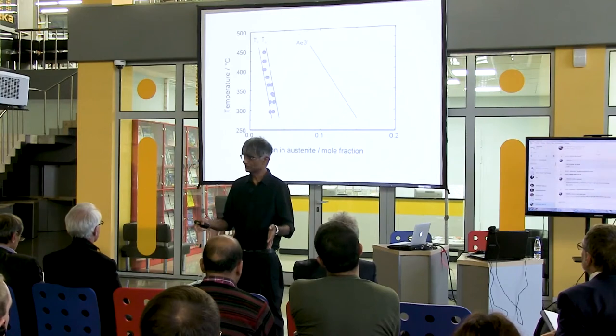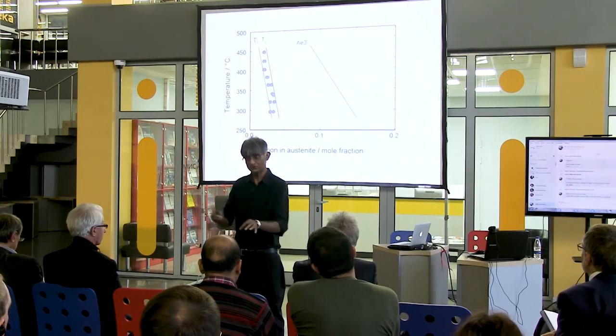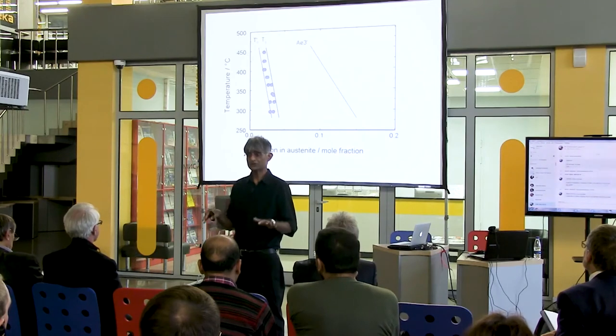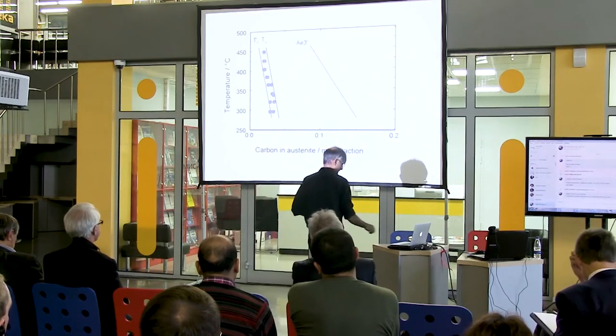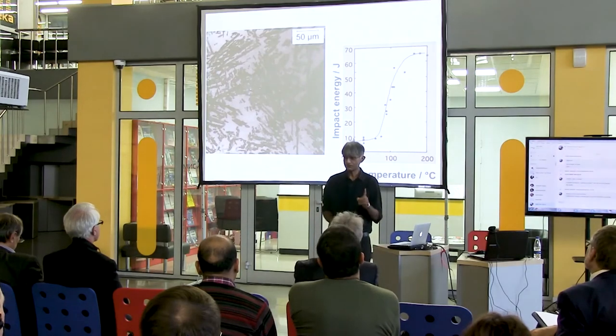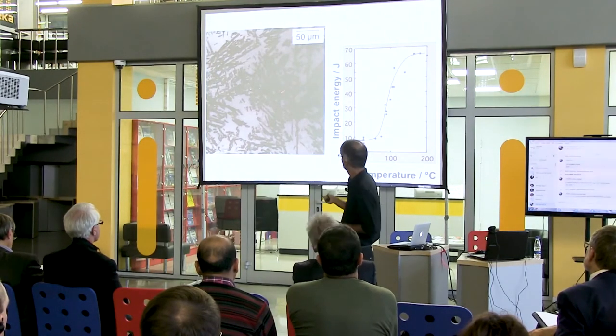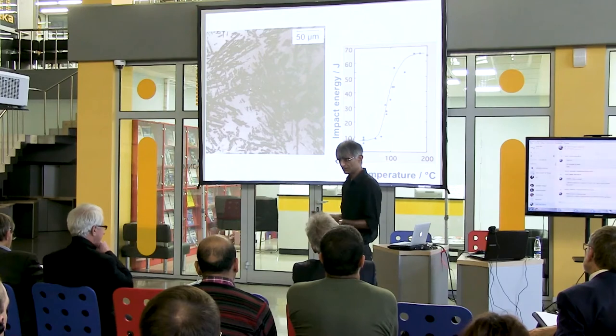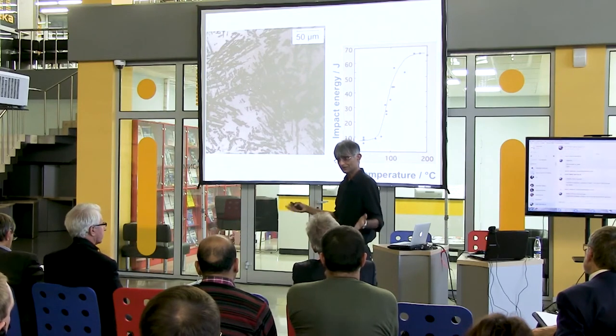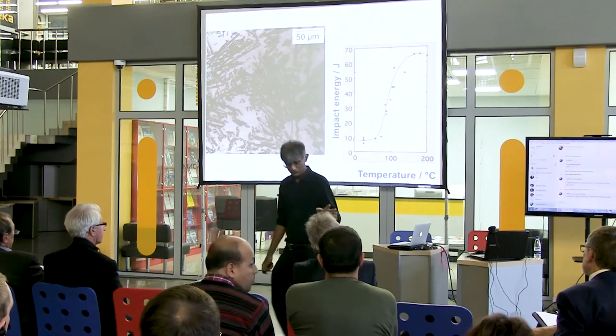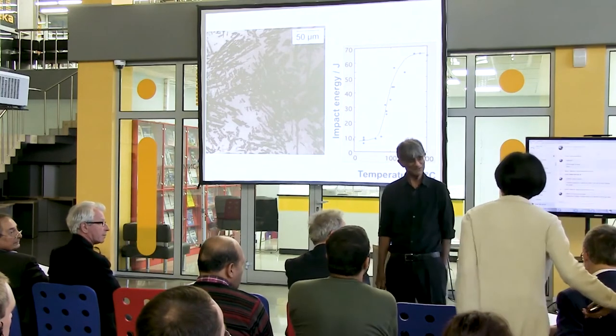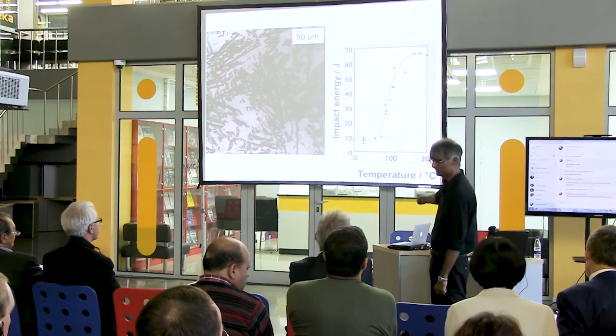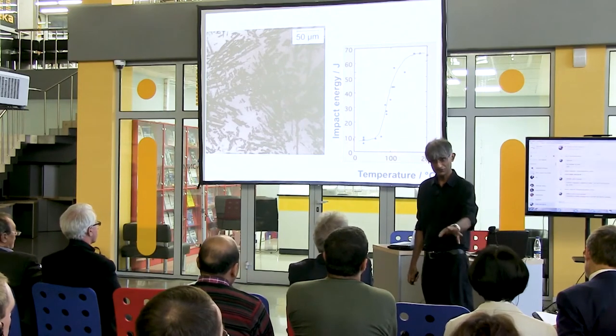This is a macroscopic measurement — it doesn't take account of the inhomogeneous distribution of carbon. On average, the reaction will stop when the carbon concentration anywhere in the material reaches the T0 composition. And that is why the T0 curve explains the very poor toughness — the reaction stops when these regions reach a composition of T0. After that, thermodynamics tells you it's not possible. The toughness is extremely bad, and that is the result from thermodynamics. You have these large regions which will decompose into untempered martensite.